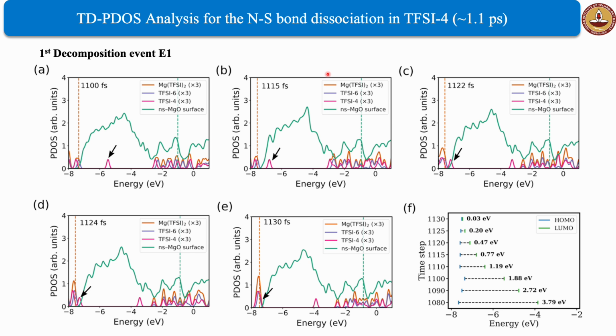Now, to better understand the mechanism of charge transfer, we analyze the time-dependent PDOS. Basically, here we looked at how the LUMO of the TFSI anions evolves with time. Here we can see that the LUMO of the TFSI 4-membered ring is well below the Fermi level of the surface, which indicates the feasibility of the charge transfer.